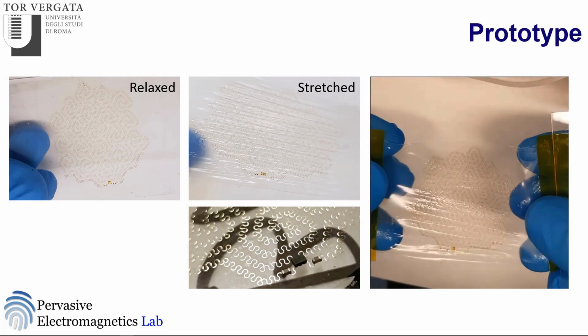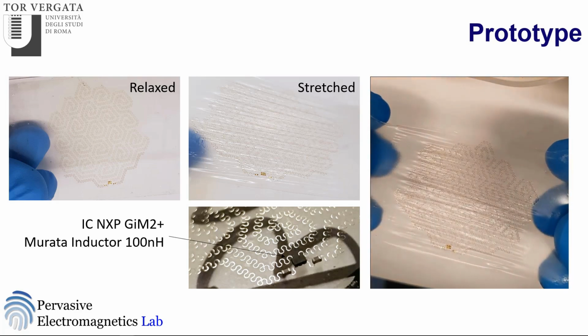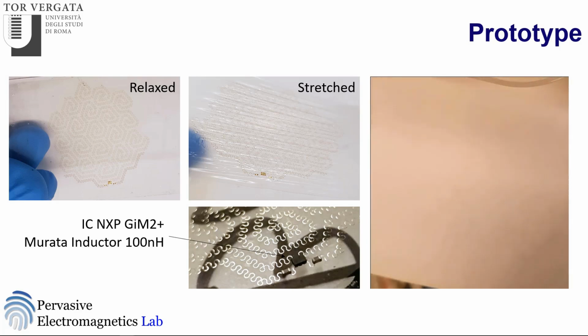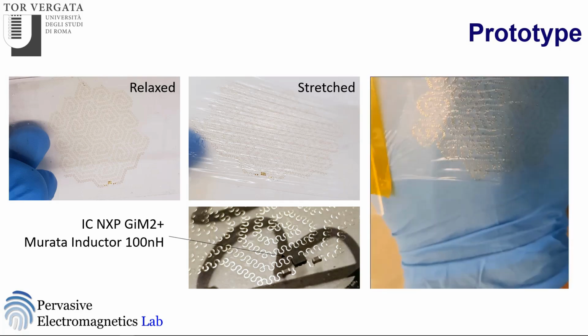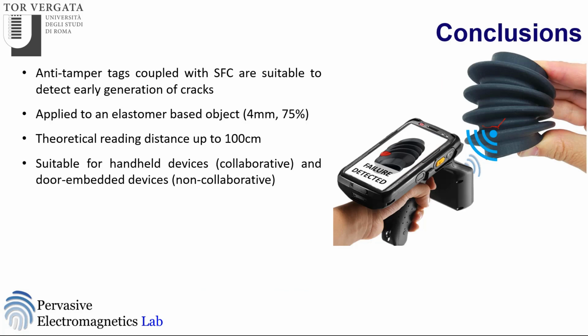Here is reported the prototype. Starting from the relaxed to the stretched condition, the device seems to follow the deformation without failures, as shown in the short video clip. So, in conclusion, we can say that an anti-tamper tag coupled with a space filling curve is suitable to detect early generation of cracks. Here it has been applied to an elastomer-based object, and a theoretical reading distance up to 1 meter has been achieved. So this is suitable for handheld devices, so collaborative, or door-embedded devices, perhaps non-collaborative scenarios.